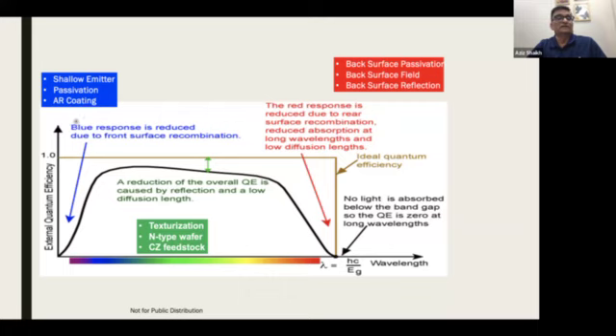So on the front side, what has been done is, as I said, if the junction is very thin, you can improve the carrier collection. So the shallow emitter, that means higher resistivity junctions, passivation, and the anti-reflective coating, so the light doesn't reflect. On the back side, putting a surface field on the back side, so if the carriers reach the back side, they are reflected back. There is also back surface passivation and back surface reflection. So all these schemes are used, which translate to new design structures for the devices.